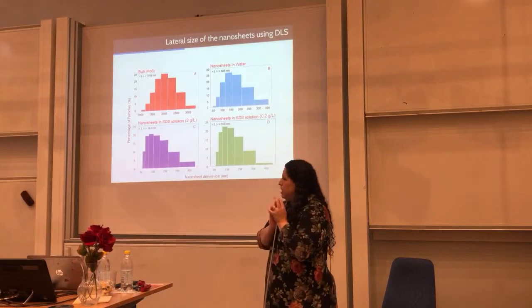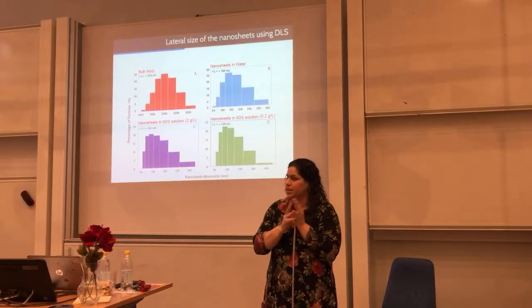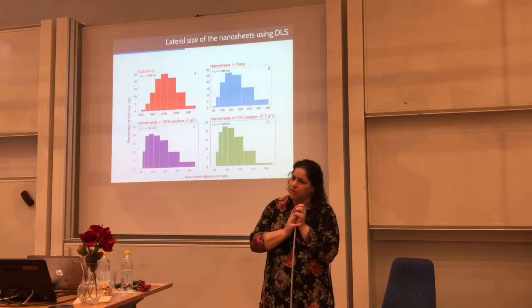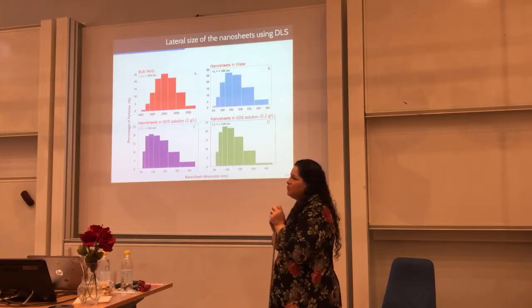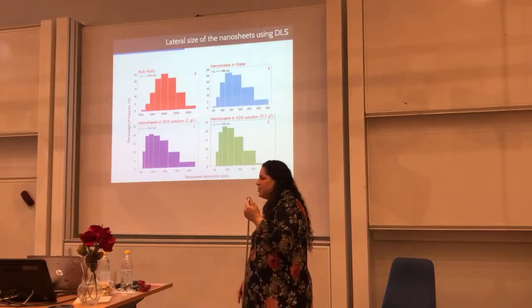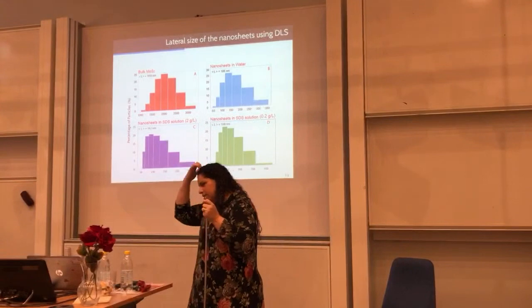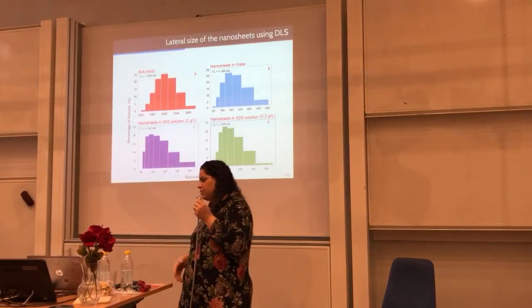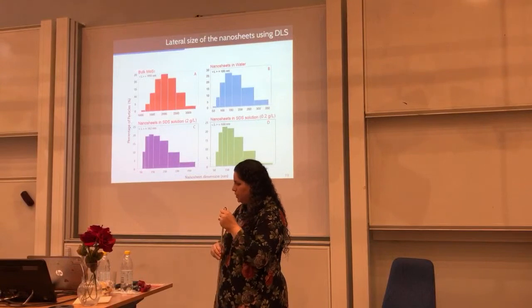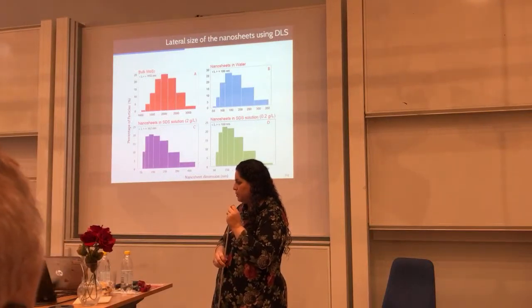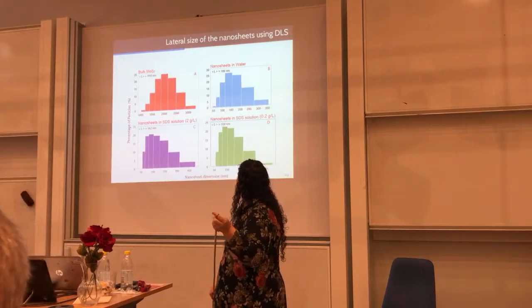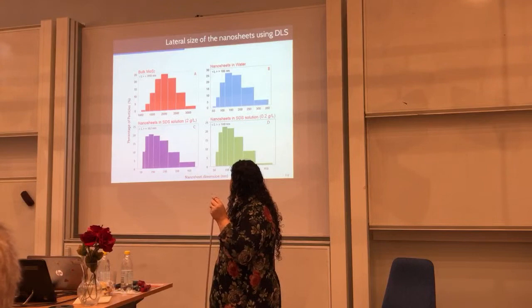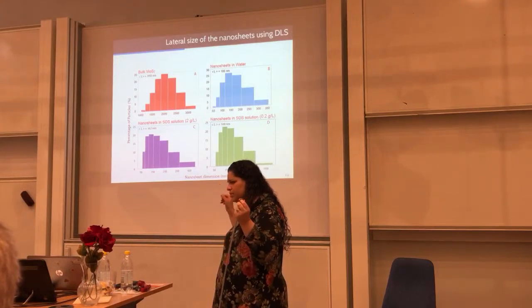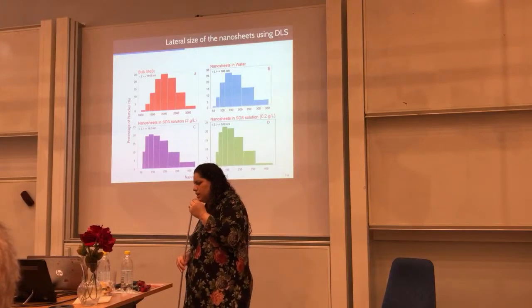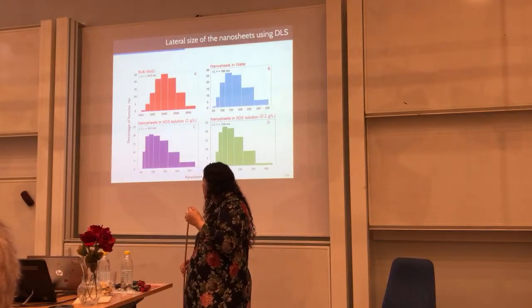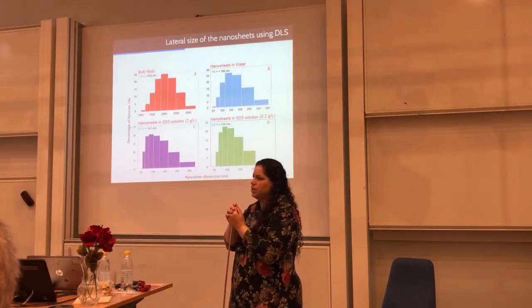Then we talked about the thickness of the layered materials. And now we wish to talk about the size. If we have to use the AFM and the TEM to measure the size of the particles, it will take forever. So there is also a need to look for techniques that we can use to circumvent the use of techniques that take too much time to evaluate. So we use DLS, dynamic light scattering, to evaluate the size of the particles. And these results relate to the results using the other techniques.